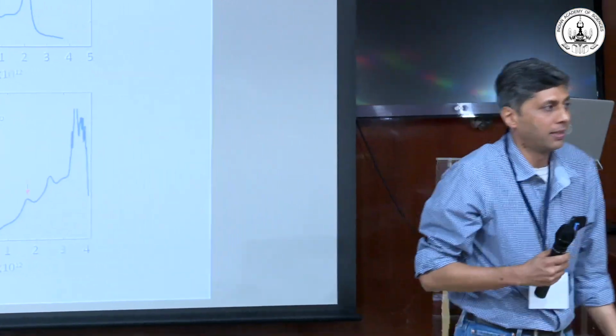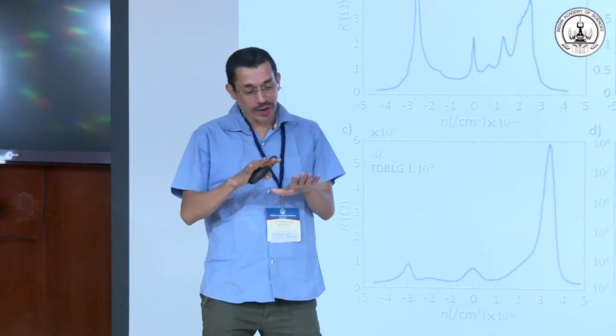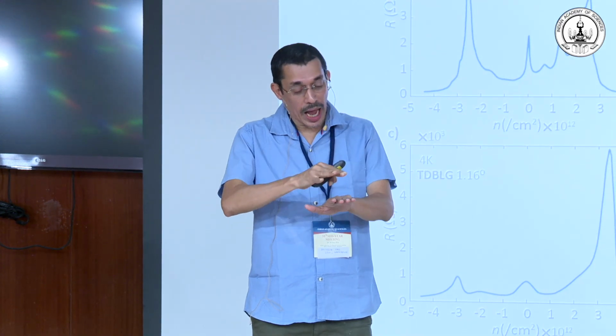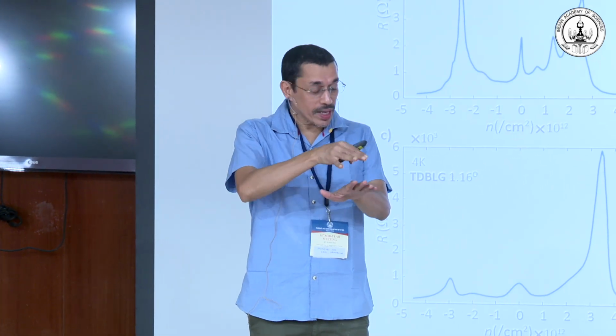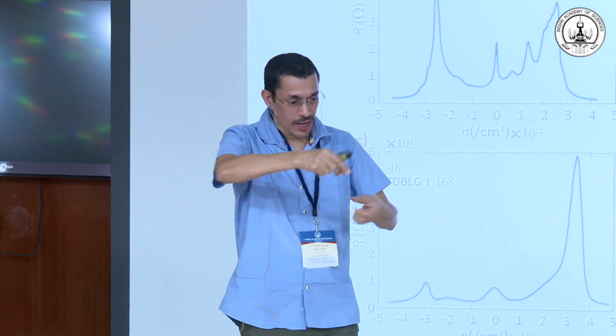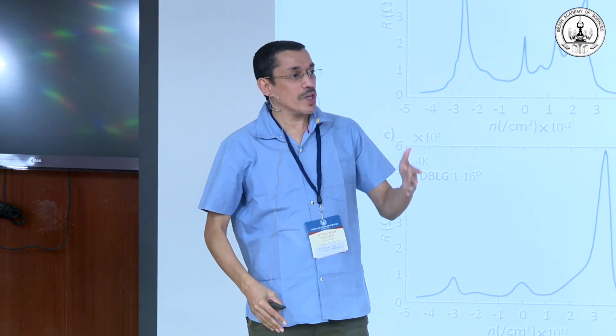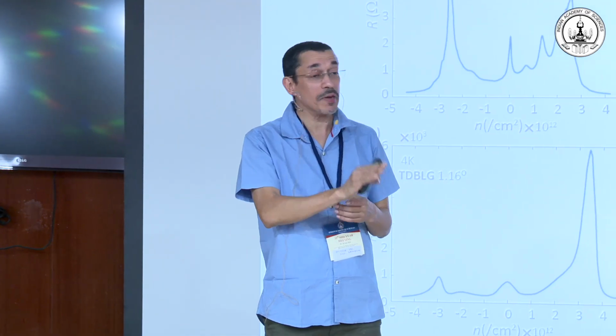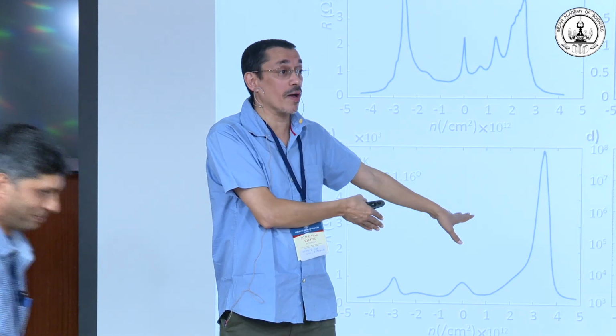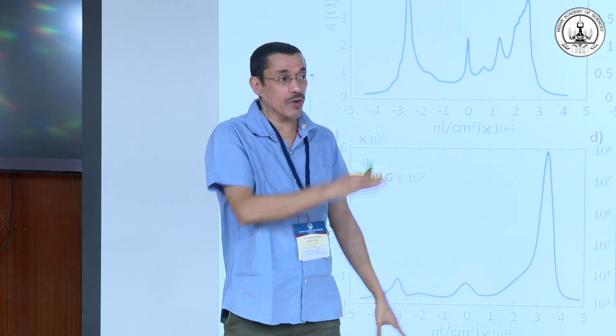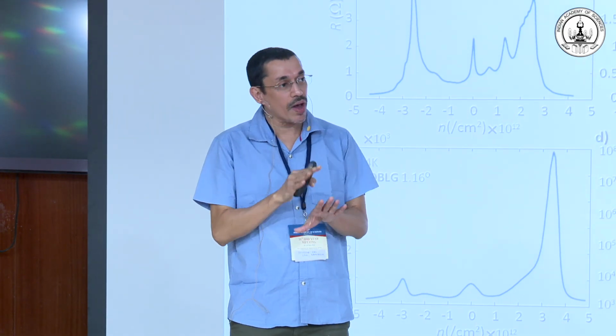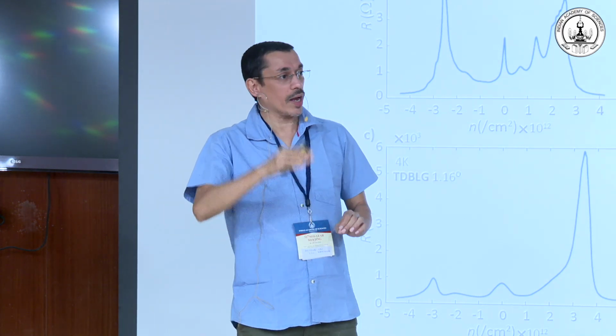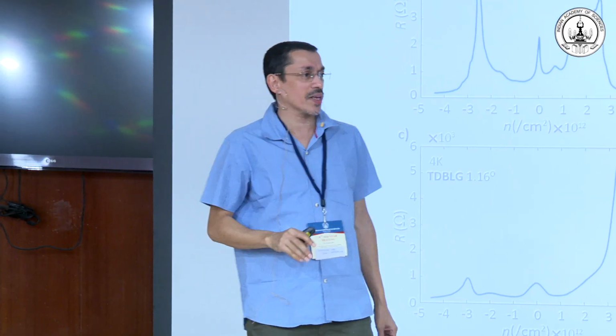Actually, this is a good time. It's a very stupid question. So making that sample, you have to take the measurement immediately, or can it stay in that particular configuration? That's a very interesting question. The relaxation I was talking about only happens during the making of the devices. Once the device is ready, meaning you land it and the contacts are defined, even after 2 years, 3 years, nothing changes. The characteristics of the device are in fact much more robust than the graphene samples, we have realized. Experimentally, these devices are very robust. Once contacts are formed, you can go to low temperature, room temperature, many thermal cycles, and nothing changes the characteristics.